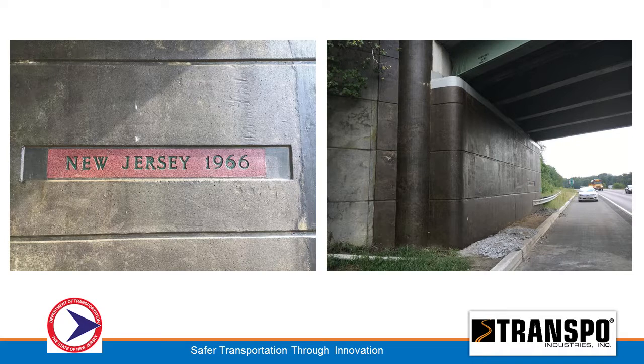Q: There appeared to be some surface scaling in the before pictures — did you do any concrete repairs before applying the material? Yes. You can see above the date stamp there was some hollow concrete on one of the structures. Anything that was loose or hollow was repaired using standard methods — get under the rebar, chip it out, and pour. We used RapidSet, so 24 hours.